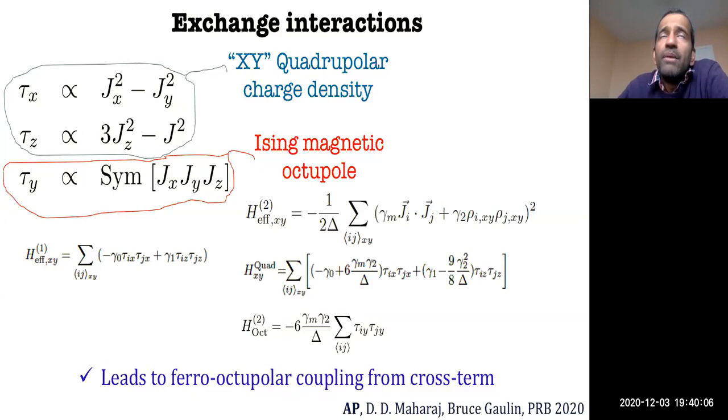But if you apply a small enough field to somehow kill off what you think might be impurity physics, then it looks like you get something which is not simple linear response. The problem, I think, is that you have to eliminate other sources. If you have some kind of Van Vleck contribution, you have other contributions that you have to imagine subtracting off before you can do this.